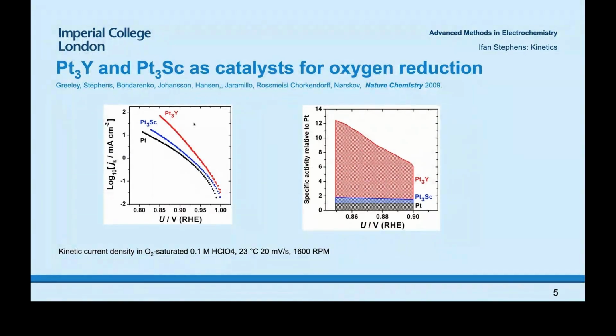If I hadn't gone through the steps of actually making sure that we could get reproducible data and making sure that what we did was comparable to the literature, we wouldn't have been able to prove that this platinum yttrium catalyst was as active as it was, and we wouldn't have had credibility from the wider electrochemistry community. So the main take-home message I want to say about this is that benchmarking catalyst activity in a correct way, and doing it in a way comparable to the literature, is really important.